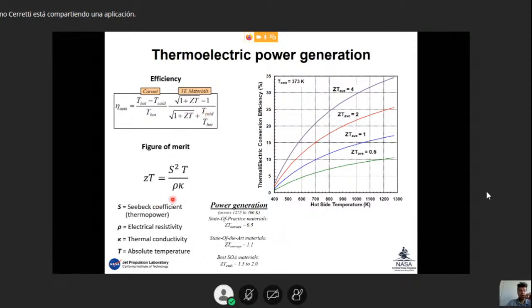a dimensionless parameter which is a function only of the thermoelectric materials that are used. It's the product of the Seebeck coefficient squared times the temperature, over the electrical resistivity and the thermal conductivity. Now, the goal of NASA for the new generation of thermoelectric materials, or in general devices, is to reach conversion efficiencies of about 20%. That 20% means that the higher the temperature, the lower the average ZT we need, which is this term here. It's the average value of ZT over the temperature range we are considering.